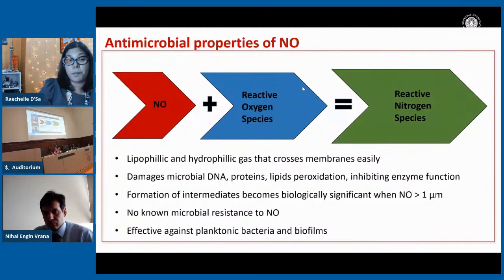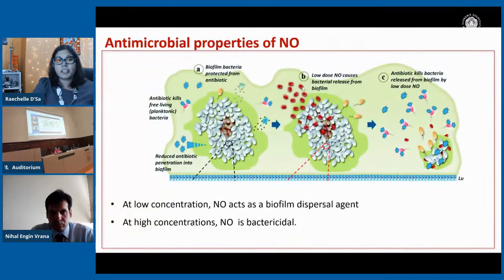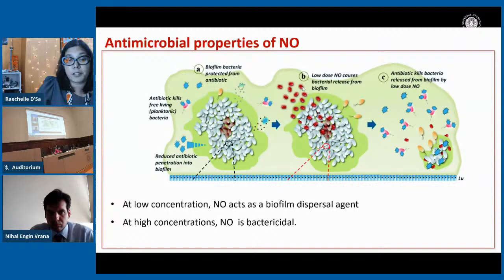Nitric oxide is also good because it's effective against planktonic as well as biofilm bacteria. The amount of nitric oxide that is required for its antimicrobial properties is concentration-dependent. At low concentrations, nitric oxide can act as a biofilm dispersal agent, so that if you have another antibiotic or something else in there, it can disperse the biofilm and the secondary agent can kill off the infection. Or at higher concentrations, above 1 micromolar, nitric oxide can be bactericidal.